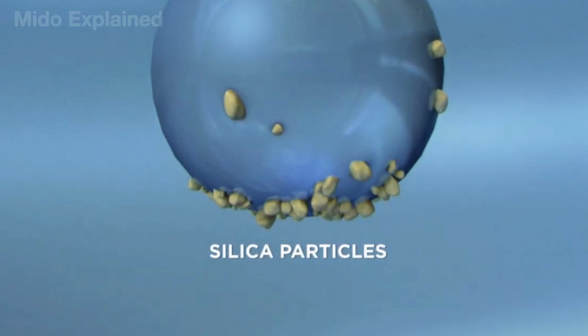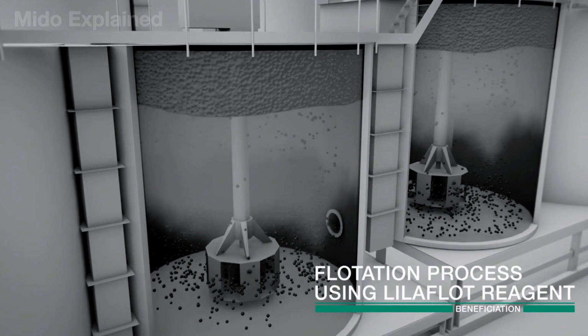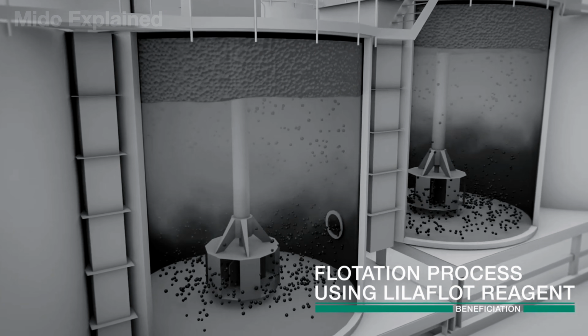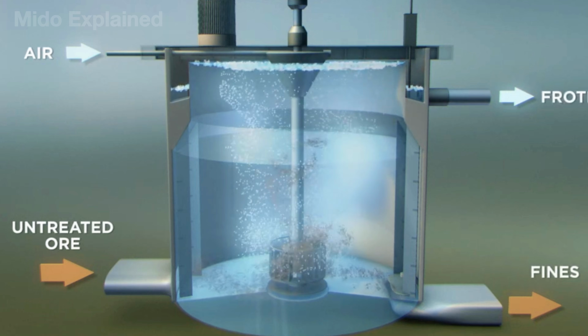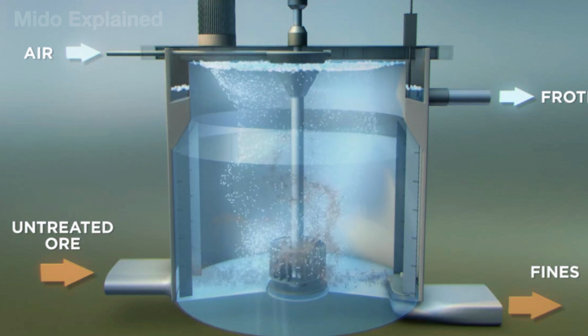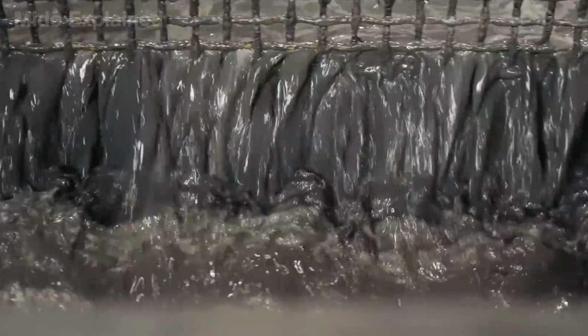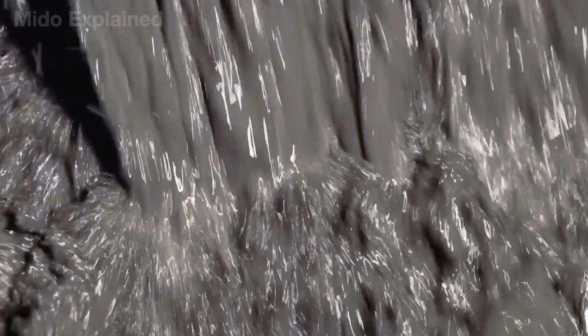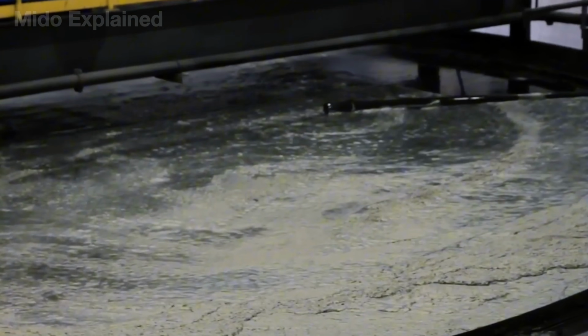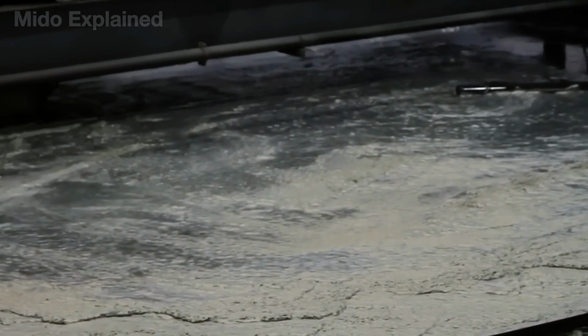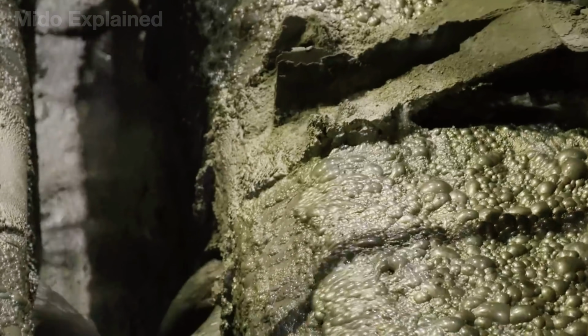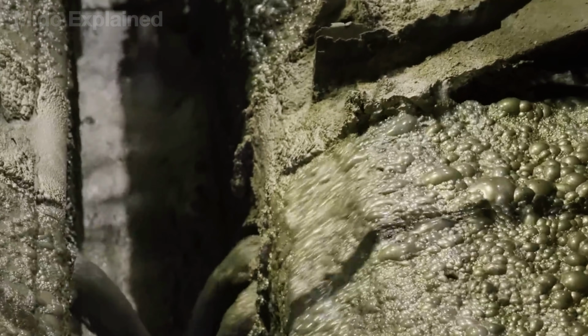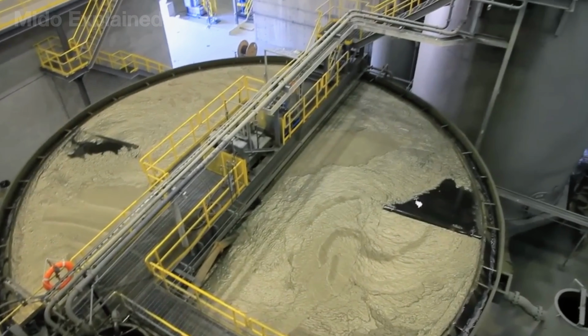The target mineral particles adhere to the surface of the bubbles and gradually float to the surface, while most of the soil and rocks sink to the bottom. This mixture usually remains in the flotation tank for about 5 minutes before the mineral-rich foam layer is continuously scraped away for recovery. Thanks to the flotation process, the iron content in the concentrate can be increased from about 35% to over 65%, while most impurities are removed, creating a high-quality raw material.